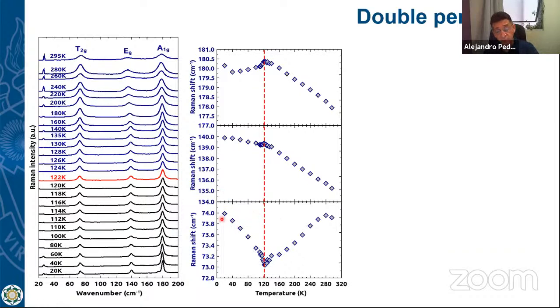And you can see that, in fact, we really have a change in the behavior of the phonons. The phonons, remember, they are associated with the structure, and this kind of behavior is very well known in vibrational spectroscopy, which is called soft mode, because the mode is becoming soft when you go near to the phase transition. And this kind of transition sometimes is associated to a ferroelastic transition, where we can have different states of stress inside the crystal.